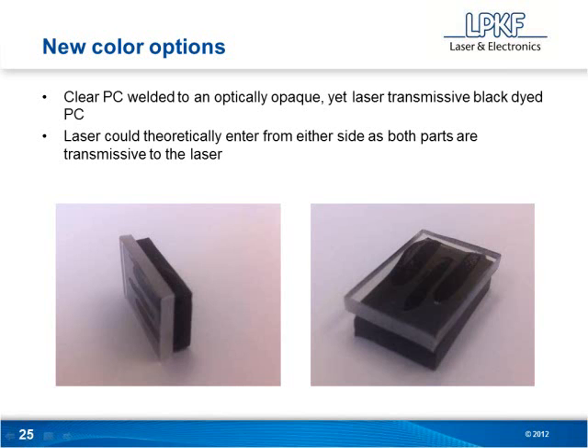This being said, with the 2-micron technology, what we're able to do now is we could theoretically bring the laser in, and I believe we did this in this case, we could bring the laser in from the black side and still weld these plastics together. So the laser would be passing from the black through to the clear. This opens up possibilities. We've had a few requests for this, or at least just more information for automotive lighting, where you're limited on the colors of plastics that you're trying to weld together. And so again, this is what I was talking about as far as color combinations and joint designs. We're opening up a lot of opportunities for how we can approach these now.